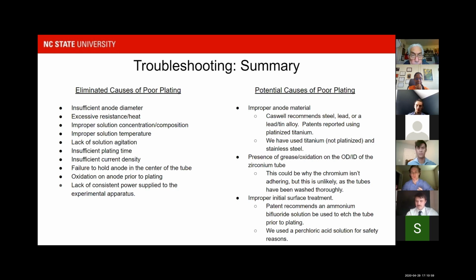So we don't believe it was a failure to hold the anode in the center of the tube. We were very careful to make sure that the anode was directly in the center, and we don't believe there was a lack of consistent power or anything like that. So the three causes that we thought were most likely culprits were an improper material. We used stainless steel rather than lead, and we also used titanium, but we could use lead or lead-tin alloy or platinized titanium, but we didn't have access to those materials. We think it's possible that there could have been some grease or industrial lubricant on the surface that we weren't able to remove with our initial perchloric acid etch. But again, we don't think that was all that likely, although it is possible.